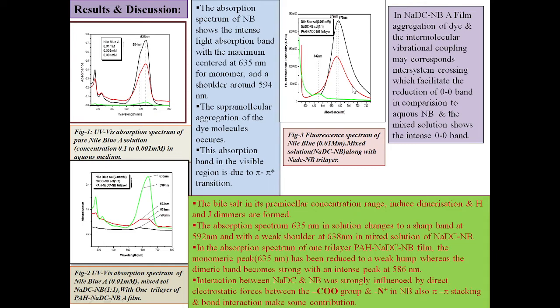Now in fluorescence spectroscopy, in the NaDC NB film, aggregation of dye and intermolecular vibrational coupling may correspond to intersystem crossing, which facilitates the reduction of the 0-0 band in comparison to aqueous NB, and the mixed solution shows the intense 0-0 band.